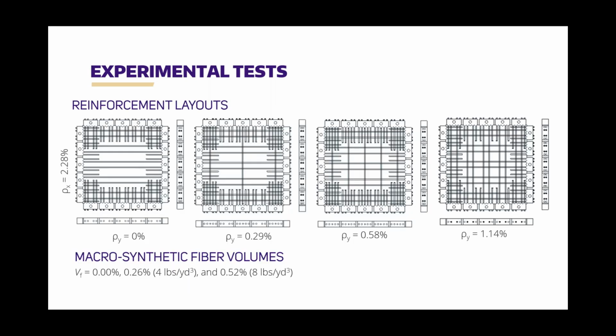What does that look like in pictures? So you can see these are the panel specimens now. If you have 0 transverse reinforcement, you can see the test region here is in the middle, and as we go up in the amount of transverse reinforcement, we just add additional bars. And the volume fibers, again, you can see the addition rates there, 4 and 8 pounds per cubic yard.